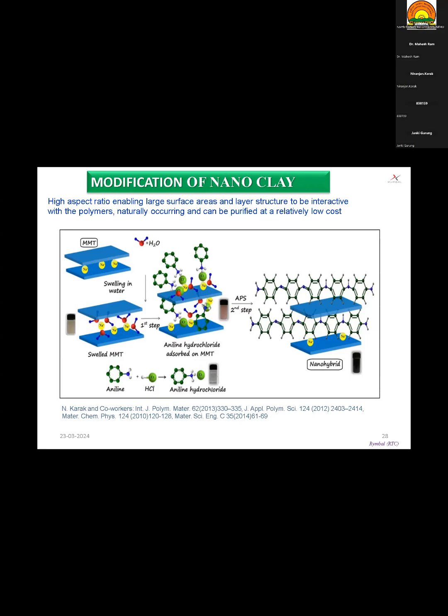Now, generally modification is done by quaternary ammonium or phosphonium ions, whereas we have tried to use a different strategy: the inbuilt modification of the nanoclay as well as making the polymer nanocomposite by using polyaniline. Aniline, we know, is an amine, and if you make the ammonium salt, which is required for its oxidative polymerization, then that will not only help in modification or swelling of the nanoclay layer, but also produce in situ polyaniline nanoclay composite by polymerization of aniline monomer through the oxidative polymerization process. So it will help to get the nanocomposite in a single shot, at the same time.